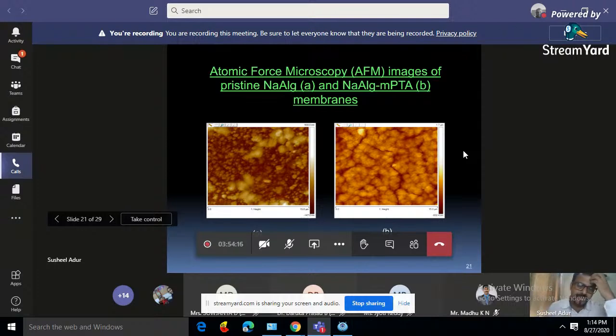And in the next one, you can see the granule-like structure in sodium alginate. This granule-like structure is because of MPTA incorporation into sodium alginate. Therefore, it shows such a structure. So we can easily prove that MPTA is homogeneously distributed in sodium alginate.